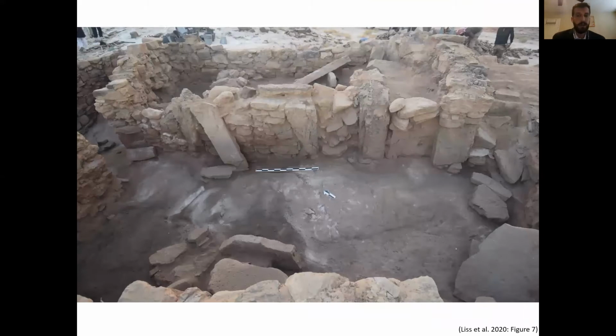One final point about the building is that at some point it was architecturally restructured. Here we are looking at that eastern half. And if you look here, we can see that at some point the entryways to this part of the building were intentionally blocked, and these blockages went all the way down to the bedrock. Because of this, we believe that this building actually had two occupation phases, one before and one after these blockages, both of which probably used the bedrock as a habitation surface.